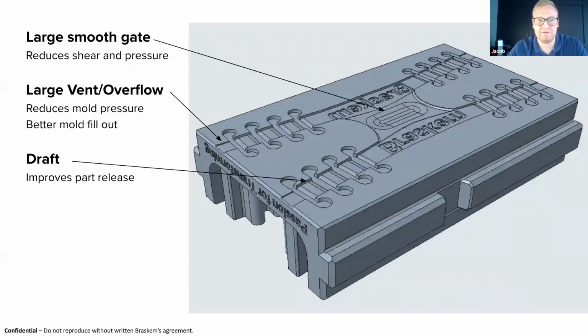We've incorporated what I'll call a large vent at the end of most of our flow paths, at the end of our cavities. This is definitely different than what we see in metal molds. In metal molds, you'll see an air vent. These are very thin sections to allow air to escape while you're molding so you don't get burning in the mold. In our case, these are essentially much thicker vents, large enough to allow plastic to flow out.